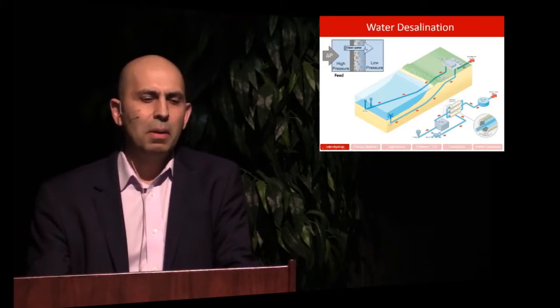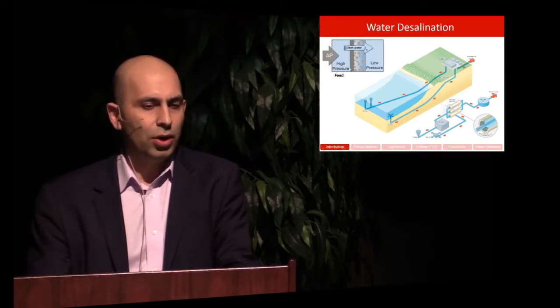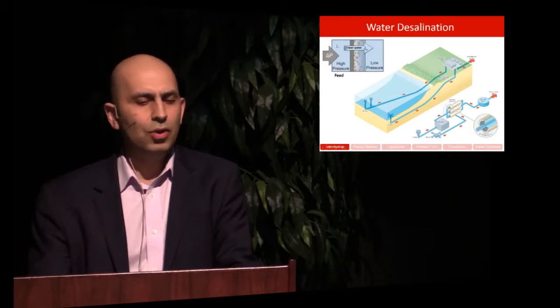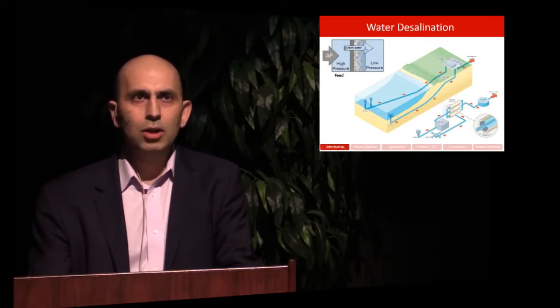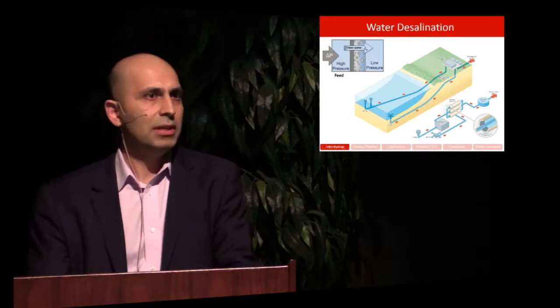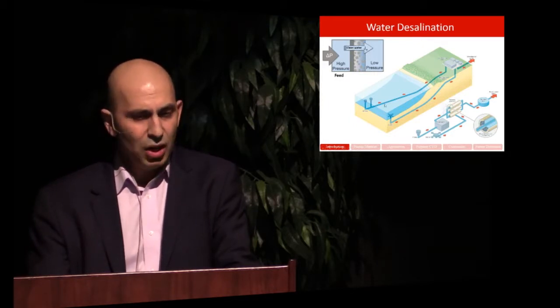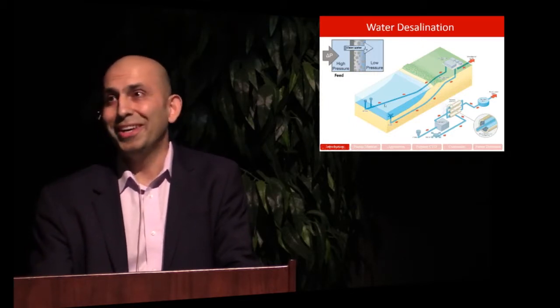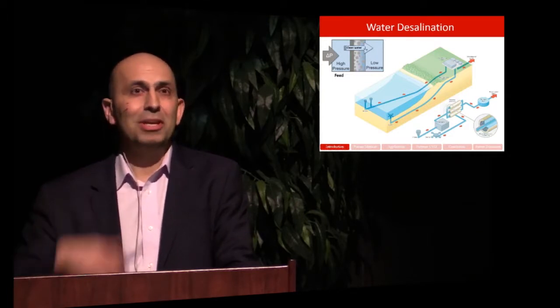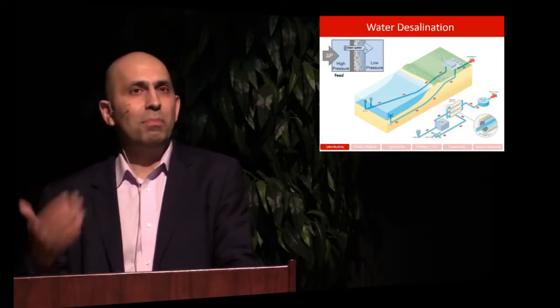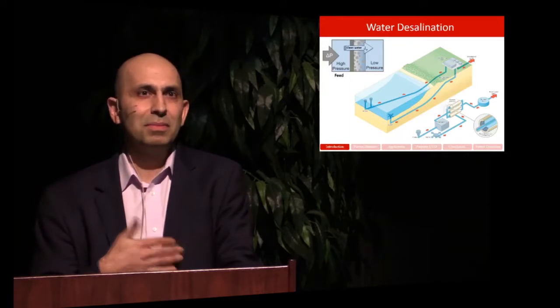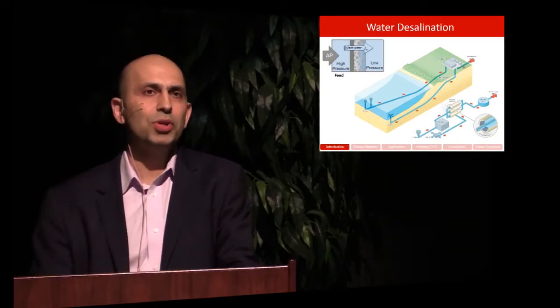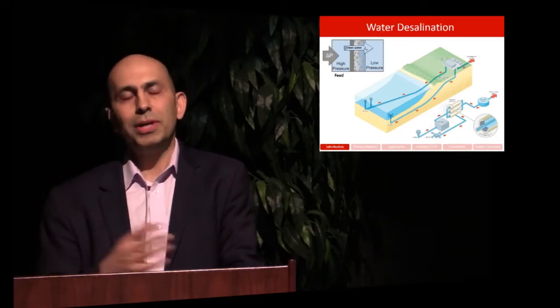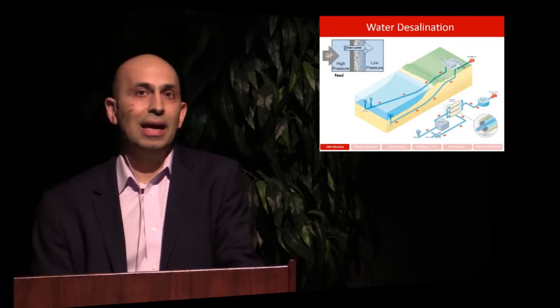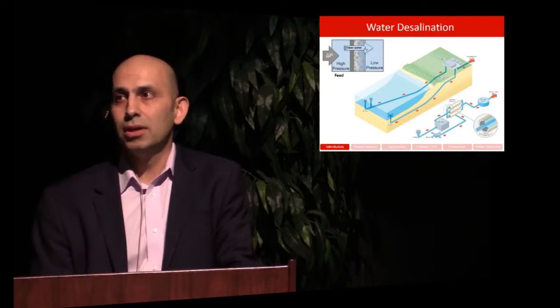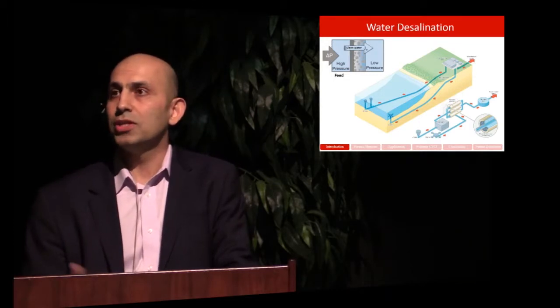So you have a selective layer that allows water to go through and rejects salt, and you have a support layer sitting under that, so it can physically support the membrane. When you are close to the ocean, you are lucky because you can just keep increasing recovery and dump the brine back into the sea. Basically, you're relying on the dilution by the ocean or by the sea. But as we go inland, this luxury is not available to us. So we need to think about solutions that are sustainable in the long term.